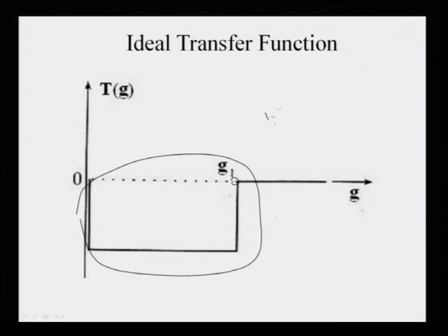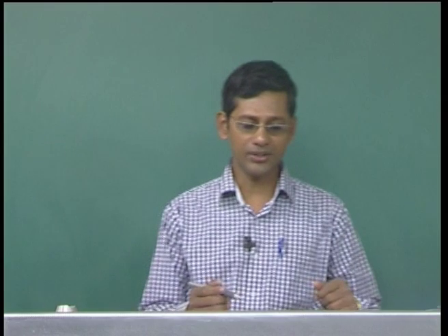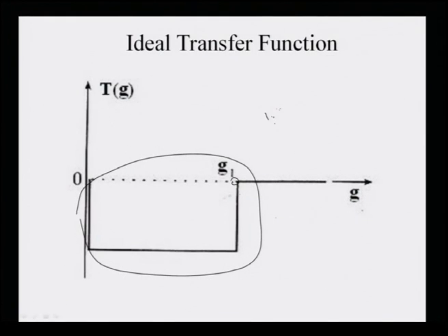Here I am showing you the ideal transfer function for a transmission electron microscope. You can see that the transfer function starts from 0, goes down, and finally, being basically a square function, reaches 0 again at a certain value of g, which is g1. Zero means less information going from the sample to the image. That is why the ideal transfer function has only one zero here, and all this information at low spatial frequency is transferred to the image from the sample.